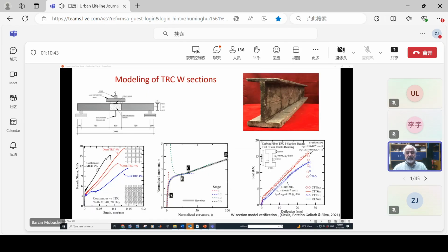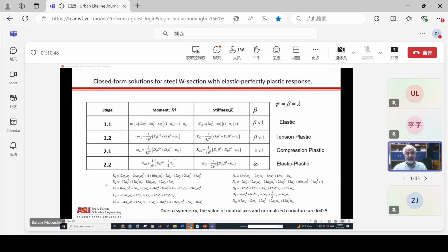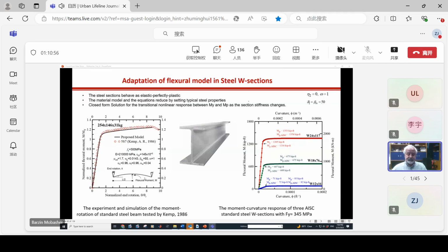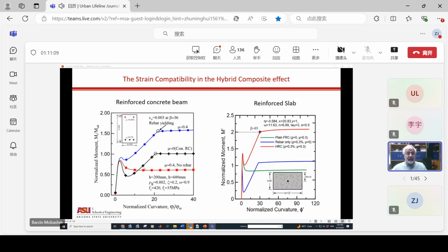These are some of the publications that have come out from our work in the last 2 or 3 years. These are all the design equations that give us the moment curvature relationship that can be put in any finite element calculation or used in closed form solutions. We can apply the same model even to steel sections and exactly fit the elastic plastic yielding in steel. But ultimately, we get a benefit of the fibers, which is shown in red, that kicks in when the steel is taking the load.